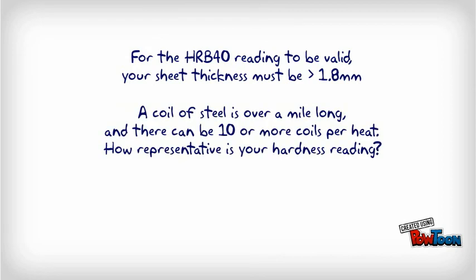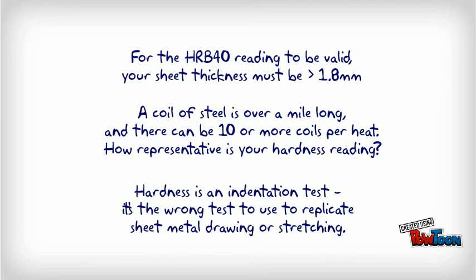Then, a coil of steel is over a mile long and there can be 10 or more coils per heat. So just how representative is your hardness reading? And finally, hardness is an indentation test. It is the wrong test to use to replicate sheet metal drawing or stretching.